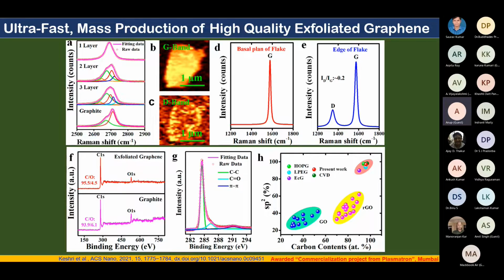When there is some kind of splitting in the peak, then it will be 2 layer, 3 layer, and the graphite which you are able to see here. Now from this, we claimed that it is basal defect free. Basal defect free means that we have done the experiment by clubbing the Raman and the AFM together.